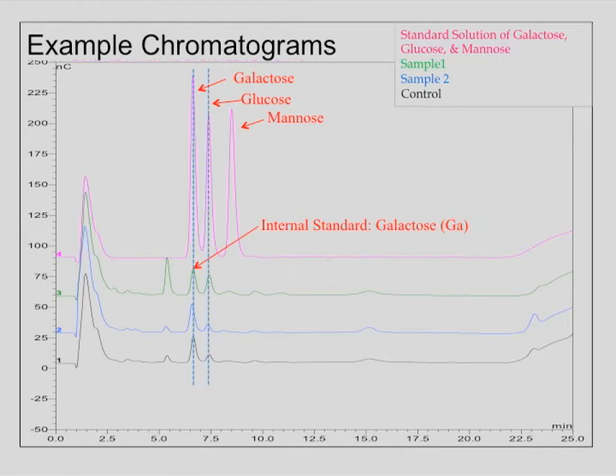So this is the Whatman control, the black line, and then the blue and the green line are preservation materials, where the blue one looks a lot like the Whatman aged in air, so you might say that one is permanent - these peaks here and here don't increase. Whereas this green one we might say is not good for preservation materials, because those peaks grow.